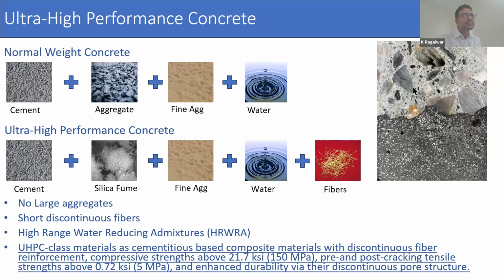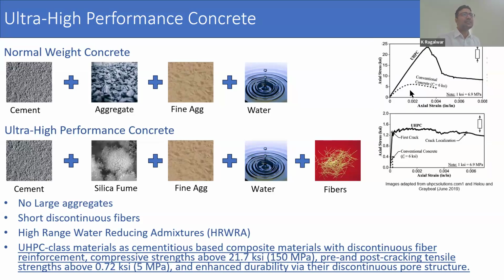So you can see in this picture how conventional concrete looks against a UHPC class material. So UHPC class material has very low pore structure and very discontinuous pore structure, and it also has no larger aggregates which can be seen in the conventional concrete. But that's why we see this difference in conventional concrete and UHPC behavior. So the first plot is axial strain versus axial stress in compressive behavior, and the second plot is under tensile loading. So we can see there is significant tensile strength in UHPC, and it also has some post cracking behavior in tensile strength under tensile loads.